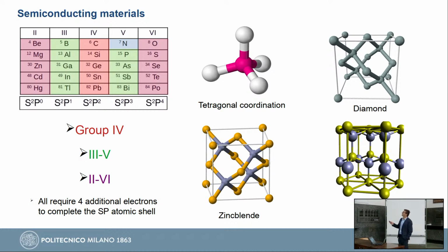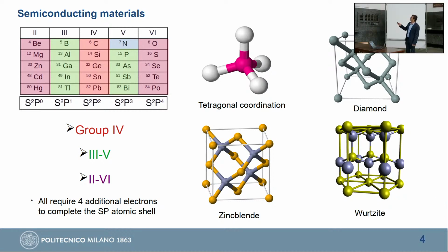And so if we take this tetragonal coordination, where we have 1 atom in the middle and 4 dangling bonds around, if we coordinate this central atom with 4 atoms, we will actually form a covalent bond while we fill this atomic shell. And so this is exactly what happens in semiconductors. So for example, in silicon, this, say, Lego block given by this tetragonal coordination is assembled in this diamond shape. In the case of 3,5 materials, a lot of them crystallize in this zinc blende structure.